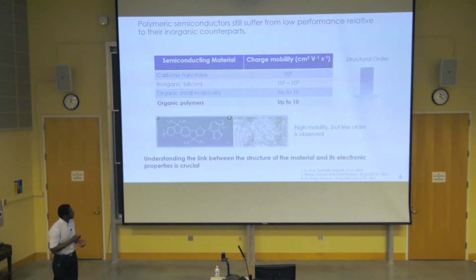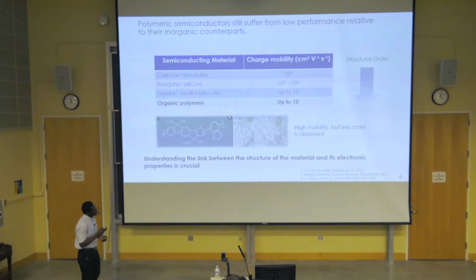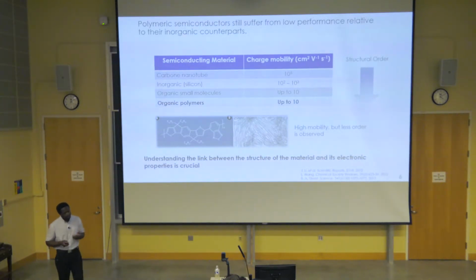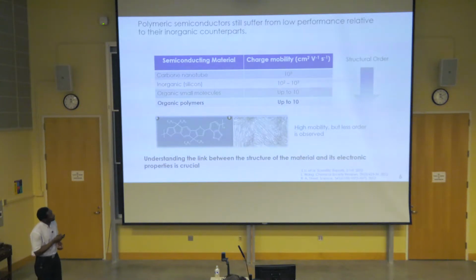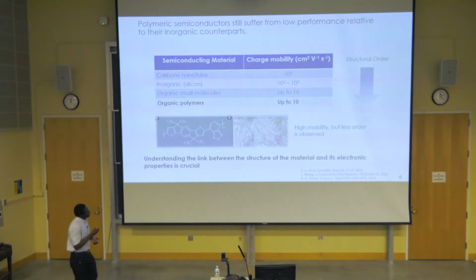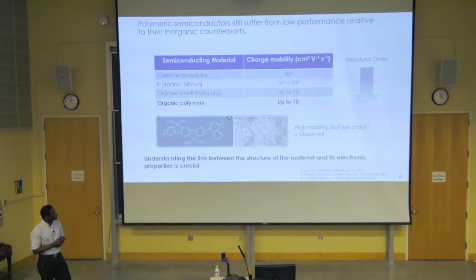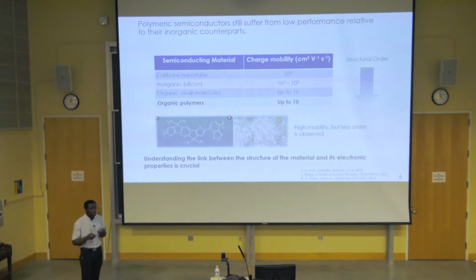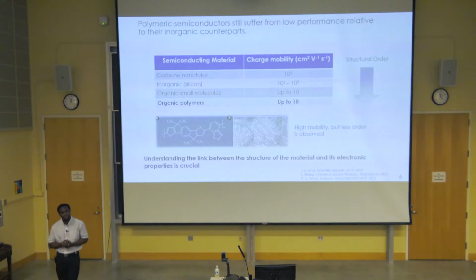But more recently, polymers with more complex backbones have been synthesized which showed a high mobility, and actually there was a jump from around 1 to 10, and seemingly less order is observed within this material. So this just highlights the fact that we need a clear understanding between the structure or structural changes within the material and the electronic properties in order to design devices with better performance.